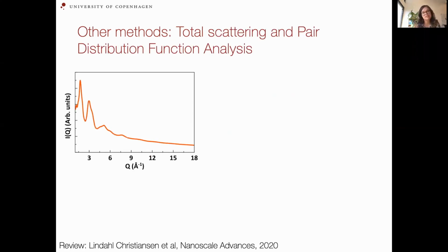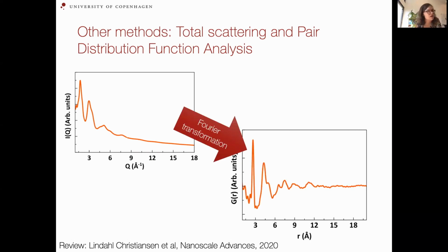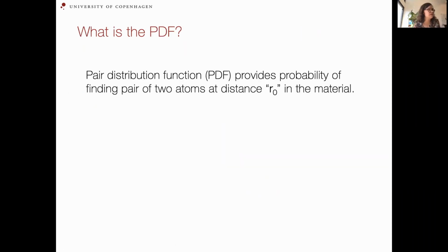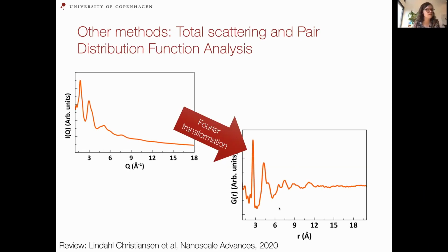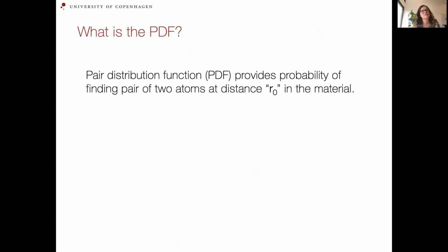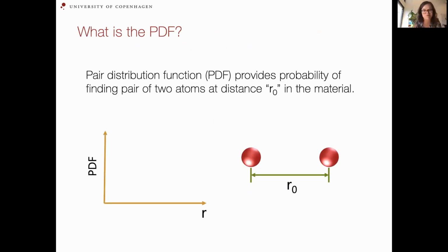So the way we like to treat these data is to take our total scattering data and then Fourier transform them. The Fourier transform means that we go from Q space, or scattering space, or reciprocal space, if any of you have taken crystallography courses, to R space, so we're in real space. Q space can be a little bit hard to interpret, and that means we now get a much more intuitive function that we can analyze. We call this the PDF, the pair distribution function. And we can analyze this in the structure, or we can first find out what it actually is.